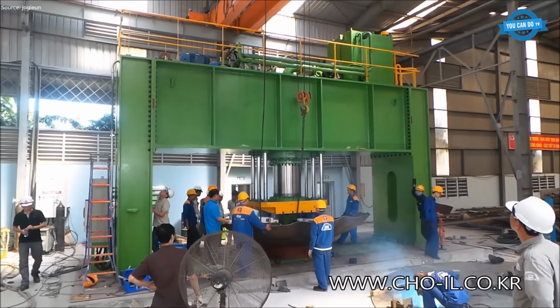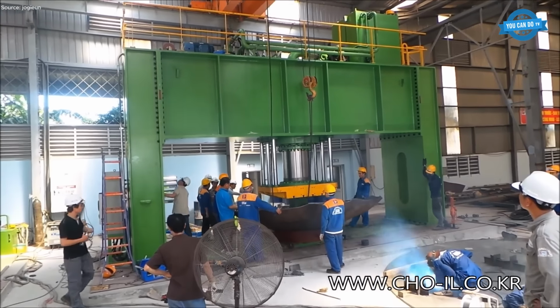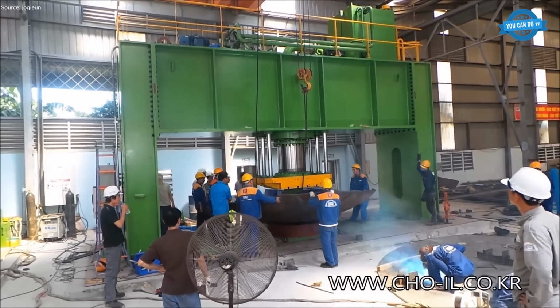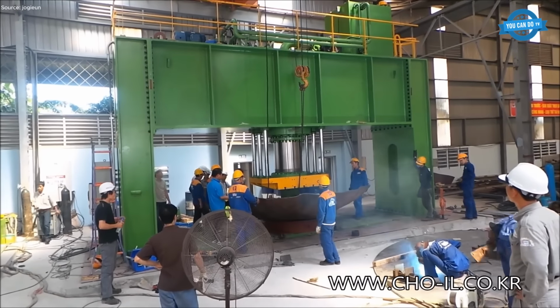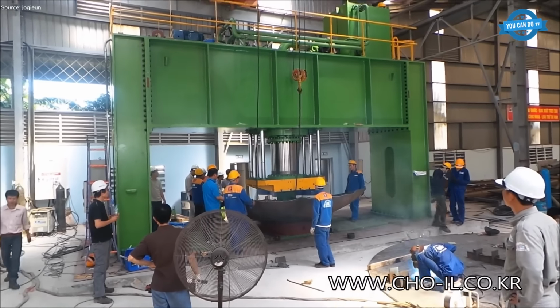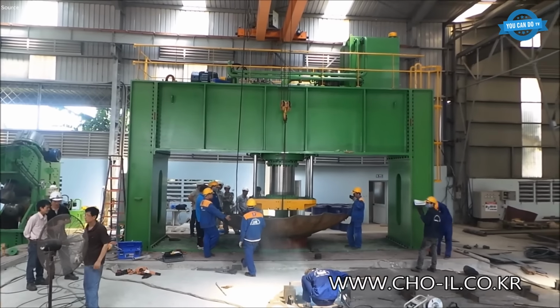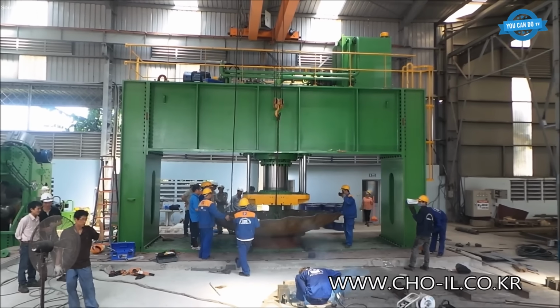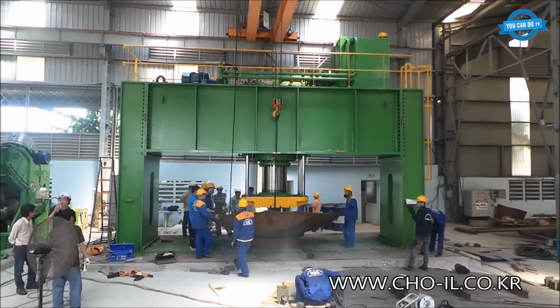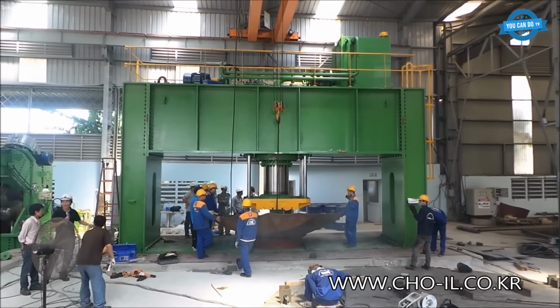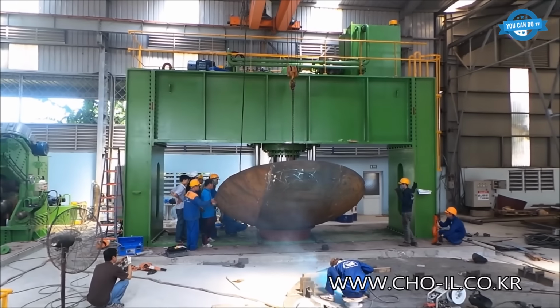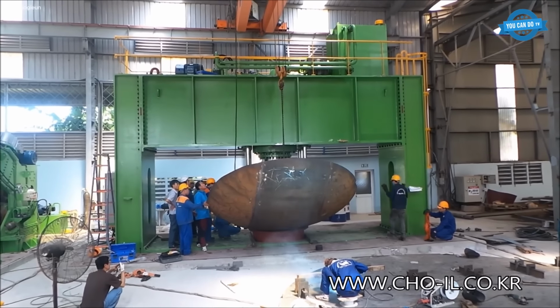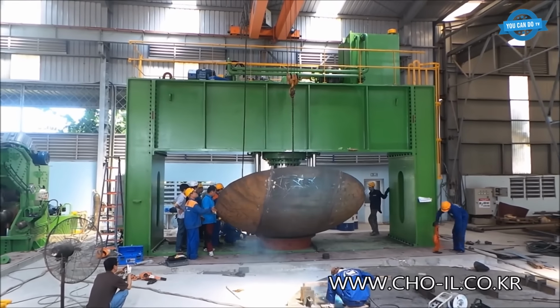Operators carefully control pressure levels, pressing speed, and die alignment to maintain consistent deformation across the entire segment. In many cases, the pressing process is performed in several stages. Each stroke of the press increases the curvature slightly, preventing excessive stress concentration and ensuring the steel retains its structural integrity. Precision gauges and templates are used to verify the curvature after each forming pass.